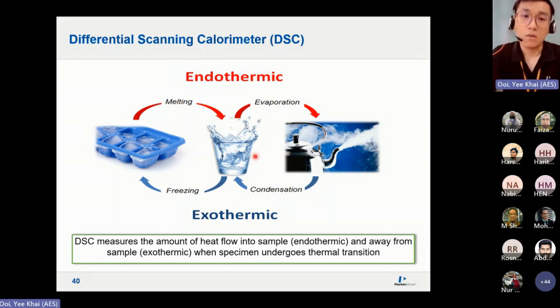But not in DSC. When you apply this onto your polymeric material, you notice that your structure doesn't change and your weight shouldn't change, because there is no change in the molecular weight, the molecular chain or the structure of the material itself. It's just the phase that changes, from solid into liquid, liquid into gas. So there are 3 phases. Melting and evaporation are always endothermic. Then condensation or crystallization, freezing, is always exothermic, meaning you release heat to the surroundings, kinetic energy decreases. Then phase transition.